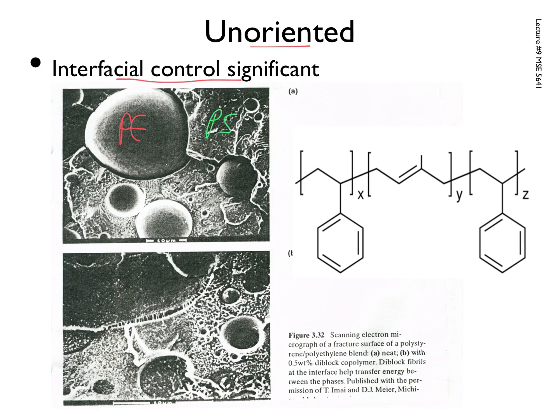If you mix polystyrene and polyethylene together, you might think they should like each other. They're both these non-oxygen containing polymer phases, but it turns out they tend to phase separate. So you mix them up at a high temperature, looks great, start cooling it down, polyethylene and polystyrene phase separate from each other, and you get complete separation of those two.